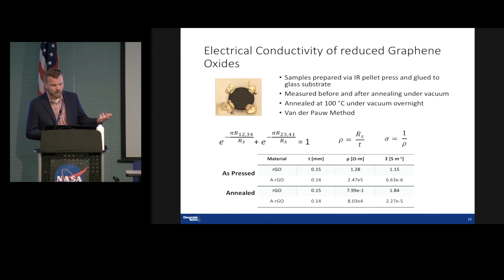And so across the thermal conditions that we tested, we are good to go for lunar applications with something like this. One of our goals in this project, as I stated, was to deal with static charge buildup. And to do that, we would have to realize a composite that was completely conductive. And so the critical result I want to show is that we've done some conductivity measurements on this reduced graphene oxide as well as our modified versions.